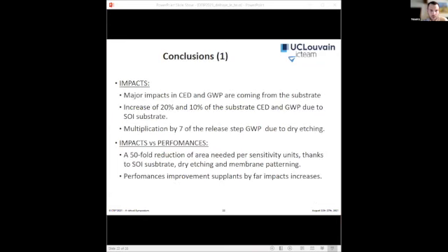So in conclusion, we show that major impacts in the cumulated energy demand and the global warming potential are coming from the substrate. There is an increase of 20 and 10% of the substrate cumulated energy demand and global warming potential if you are using SOI substrate. About the membrane release steps, dry etching has 7 times bigger global warming potential than wet etching. And about impacts regarding performances, we saw that SOI substrate, dry etching, and membrane patterning allows for a 50-fold reduction of the area needed per sensitivity units. And these performance improvements outweigh by far the impact increases.